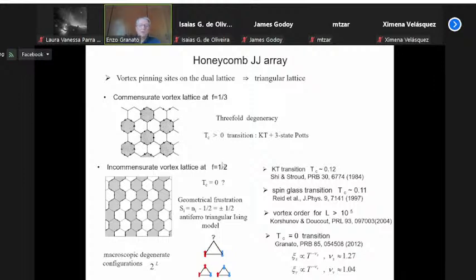But if the frustration is equal to 1/2, then you have a geometrical frustration. The ground state is macroscopically degenerate. There is a very large number of ground state configurations which have the same energy. The geometrical frustration arises because you can identify the occupation of a plaquette by a vortex with a spin 1/2. If a vortex is located in the plaquette, you call it plus 1/2. If it is absent, we call it minus 1/2.